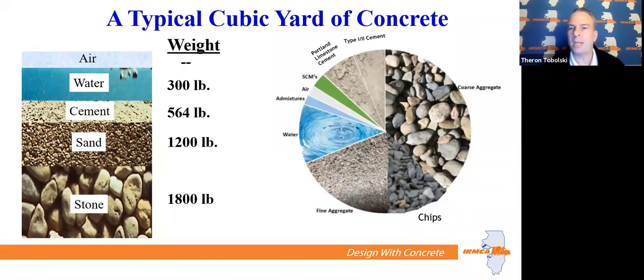But when you see on the right here, concrete is a lot more complex. You can do type 1, type 2 cement. You could do Portland limestone cement. You could add SCMs to your concrete mix, which is fly ash and slag, which is most commonly used in the Illinois market, right? There's air in there for freeze-thaw durability. There's all kinds of admixtures that you can add to your concrete mix that we'll cover in a little bit, right? We're going to have some amount of water in our concrete mix.